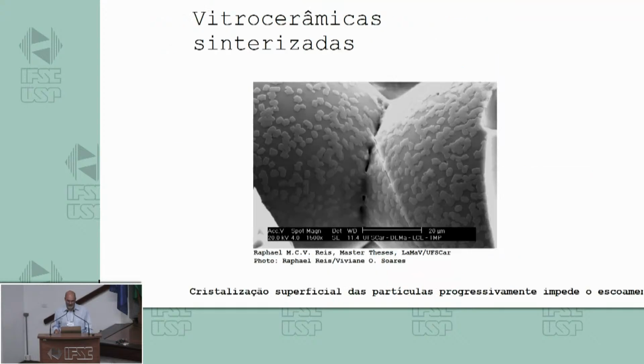The surface crystallization here is, in the beginning of the process, a problem that you have to control, because if it is too fast, it will limit the viscous flow sintering and densification of the compact, and you're going to get a porous glass ceramic. If you manage to first densify and then crystallize, you can achieve some nice products.